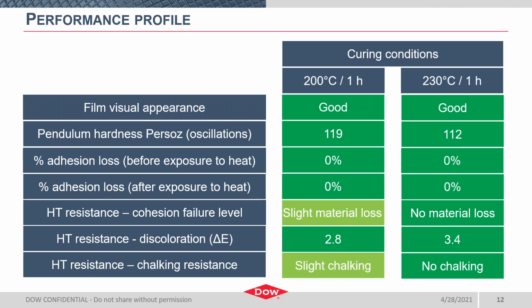Okay, so here's a quick snapshot of the performance of an 8016 base paint, comparing a 200 degrees Celsius cure to a 230 degrees Celsius cure. I'm starting to understand whether cure temperature has an impact on film performance. For both films, we measured pendulum hardness, pre and post heat adhesion according to the DIN method 2409. The degree of chalking was assessed by simply rubbing the surface of a coating after the high temperature exposure. Film cohesion was measured by the amount of dust or material peeled off during the post heat adhesion tape test.